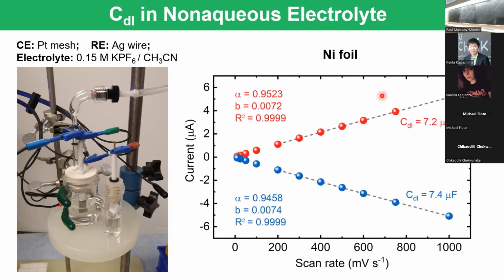Okay, then this is the fitting. Notice that we're using this power law fitting. The alpha value here is 0.95 more or less, so it's close to 1. We'll see another example later, but we try to get a value as close to 1 as possible. And from the slope, from the B term, we can get the double layer capacitance, right? So if we know this value here, 7.2 microfarads, and we divide it by the specific capacitance, the 11 that I showed you in the previous slide, we can get the surface area.